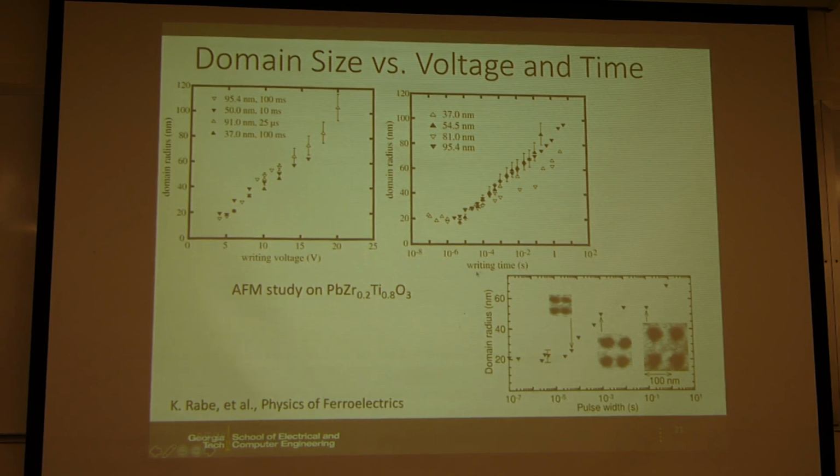In the case of writing time, it's linear with the log of time. Also notice that below a certain time, the domain saturates at around 20 nanometers. This is due to the size of the AFM tip. That's the resolution you can get from this study.